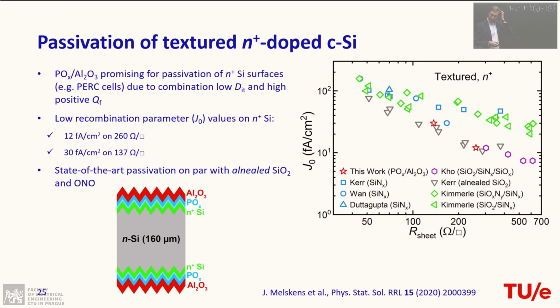If you look at different values here, these are basically state-of-the-art passivation schemes for N+ silicon. And we see stacks of, for instance, silicon oxide, silicon nitride, and silicon oxide, this ONO stack, as they call it. This is basically the best scheme that you can have at the moment. And our data points are basically in the same range. So this means that we are at least on par with the already existing passivation schemes.